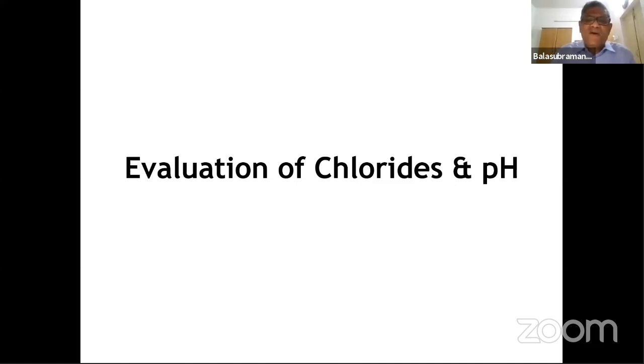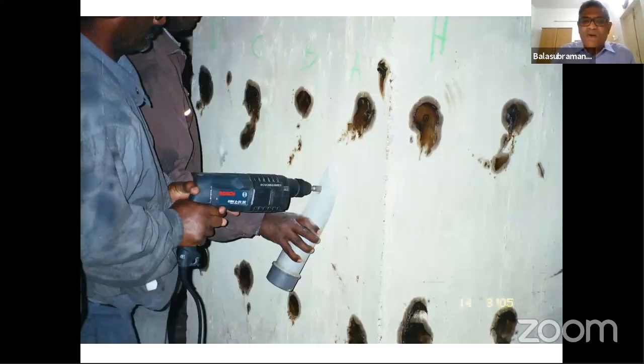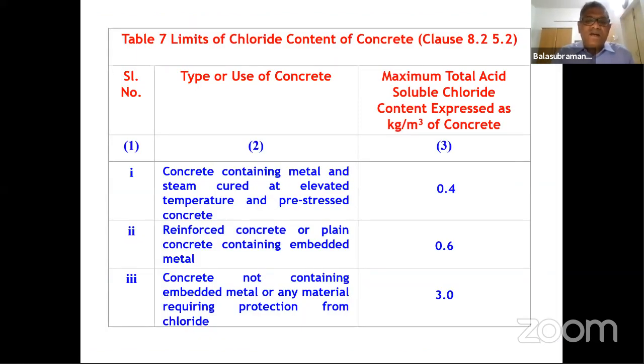Then the final one is the evaluation of chlorides and pH, which is a very, very important one, because it is through the chlorides and the pH that the steel rod gets depassivated. This is kind of a crude test, a method of taking a powder sample. We use a drilling machine and drill from 0 to 20 mm, then 20 to 40 mm, and then try to find the chloride profile. As for the limits, for reinforced concrete it is 0.6 kg per cubic meter, and for PCC it is 3 kg per cubic meter.